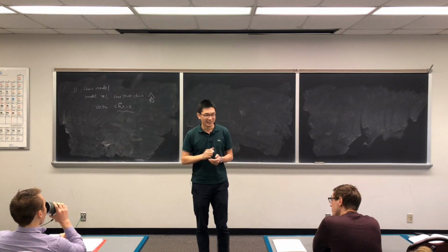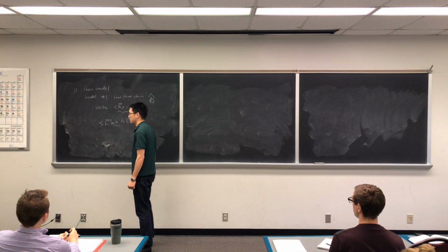Since this is not useful at all, we used another concept. In the first part of the last class, we nailed the simple math to understand how the end-to-end distance would be equal to NL squared for this particular polymer, the free jointed chain. N is how many bonds you have, and L is the length of each individual bond.